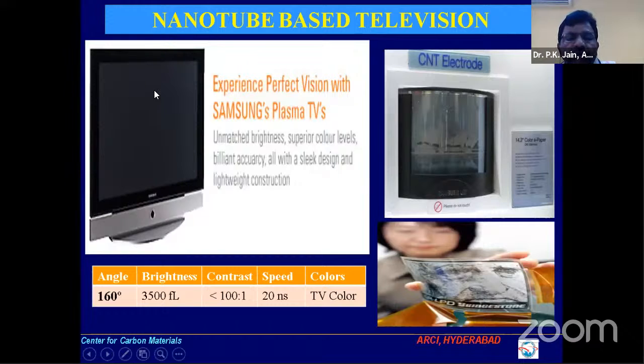It is nature that has blessed this carbon material. Now people have made the flat panel with an angle up to 160 degrees, and you cannot feel any distortion in the image. Now you don't require vacuum, you don't require anything. Even if you apply this carbon based paste onto a plastic sheet and pass a current, the image can be developed onto a plastic sheet also, because emission is happening in a very localized way onto the materials, the field emitters.